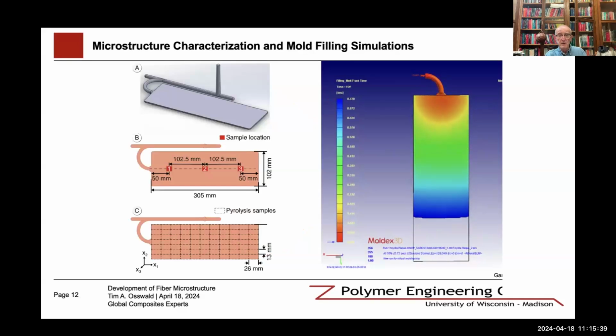So this is a demonstrator part from SABIC simulated with Moldex3D. So we have the injection molded process. We have different areas that we analyzed. You can see the middle figure on the left-hand side. There are positions 1, 2, and 3. We will refer to those. The lower part is our pyrolysis examinations that we did on the fibers to be able to predict or measure fiber content